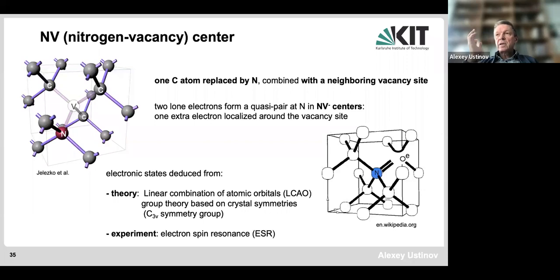How to do it is, as I said, you could, for example, bring it into the nuclear reactor, and then you need to anneal, to heat it up to high temperature, and then all the defects will diffuse away. And then if you do it right at appropriate temperature, then the most typical defect which will stay will be actually a nitrogen, which will come in because you could do it in nitrogen atmosphere, and a vacancy, which will form a kind of bound state to this nitrogen.